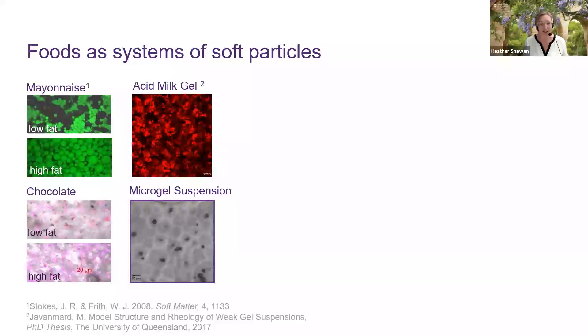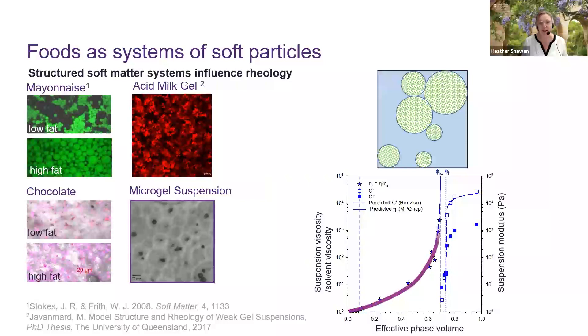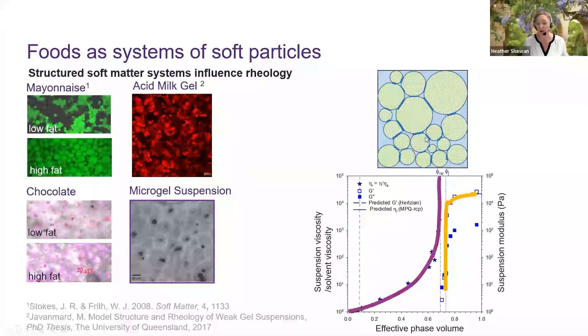Starting from my PhD, I wanted a relatively simple system, so I chose agar microgels. The beauty of soft particles is that based on soft matter physics you can structure them and influence their rheology. As we increase the volume of particles present, we increase their viscosity initially. Then as we pack them so they come into contact and deform, they become a solid-like suspension.